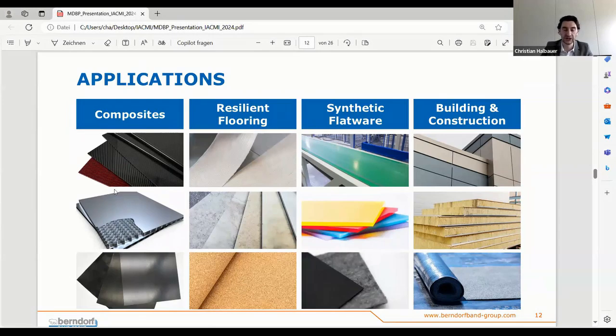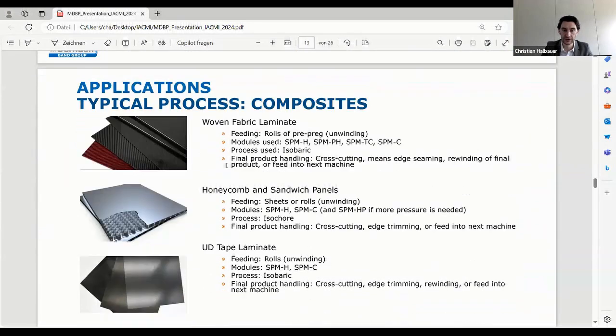This is due to the fact that our machine can run in 2 modes, which I can indicate here. For example, honeycomb products or sandwich panels might require a very low pressure so as to not damage the product. In that case, our machine is capable of running in isochoric mode, which means that we drive with a consistent gap. For other products, such as woven fabric laminates or UD tapes, it's all about the pressure that we are applying to the product. In that case, we drive with a consistent pressure. So with our machine you can choose between driving with a consistent gap, which is isochoric mode, or going fully isobaric by driving with a consistent pressure.